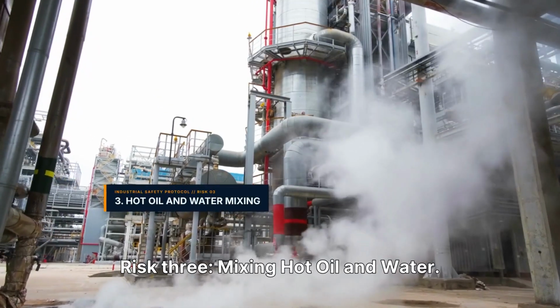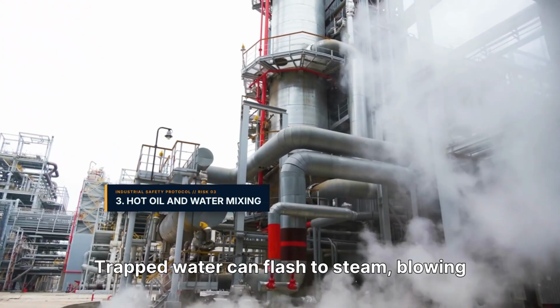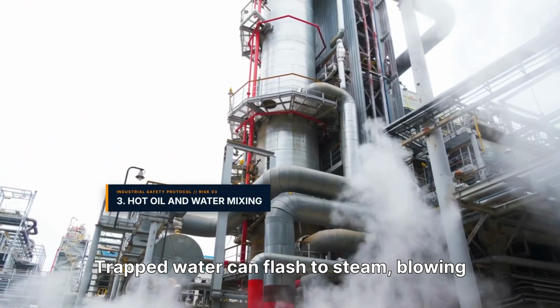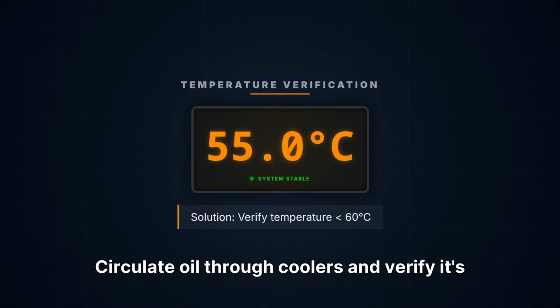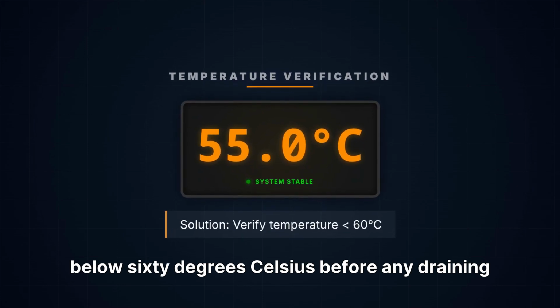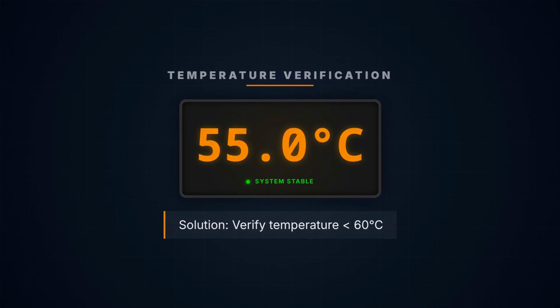Risk 3. Mixing hot oil and water. Trapped water can flash to steam, blowing hot oil out of drains. Circulate oil through coolers and verify it's below 60 degrees Celsius before any draining to open systems.